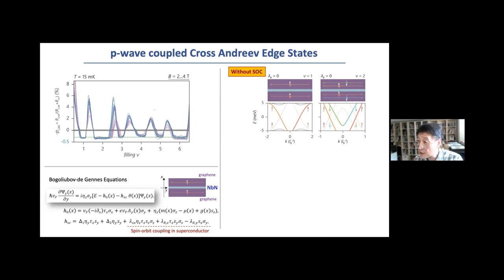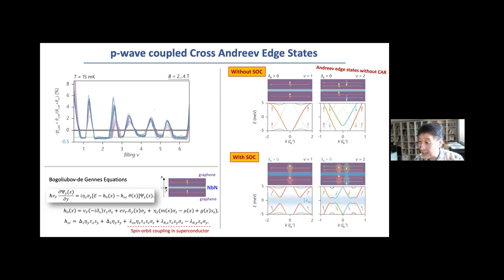Now, if you include this reasonable strength of the spin-orbit coupling, it turns out that it opens up the 2 independent Andreev states, which basically couple to each other and open up a gap, and this induced gap is directly related to the size of the spin-orbit coupling, as well as the superconductor. So that is the interesting part.